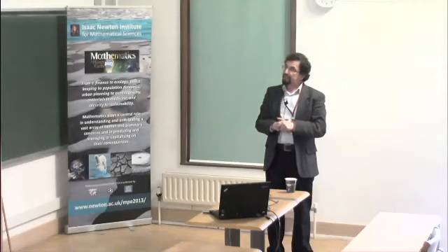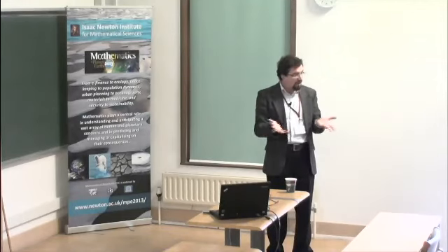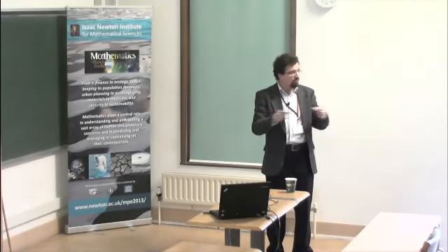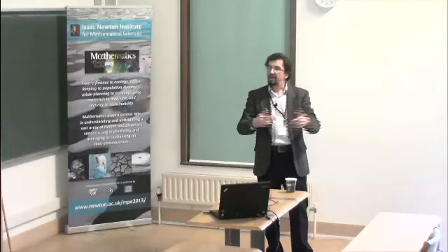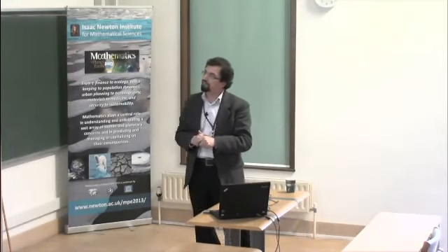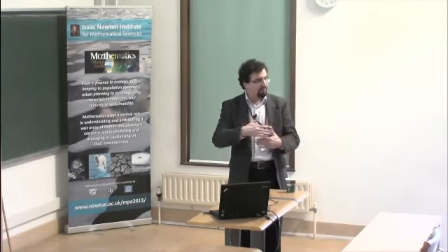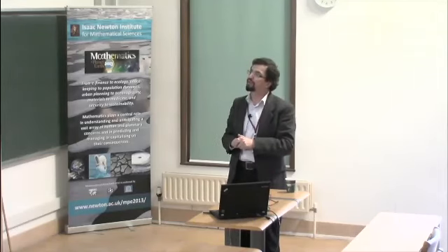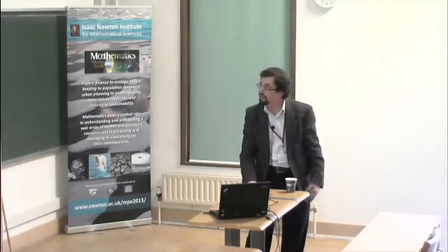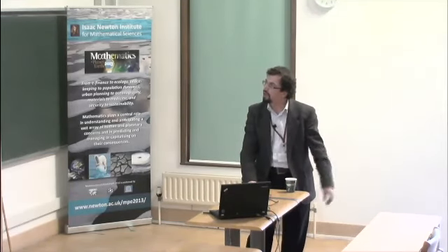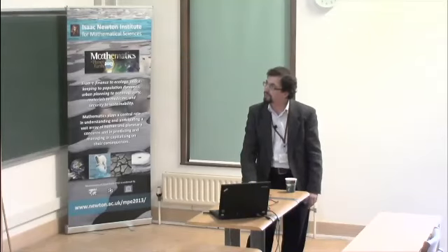But what is interesting is that X-ray shows no traces of molecular smecticity or molecular periodicity. And it's a peculiar case of a nematic phase that has some elements that are periodic, but this periodicity is apparently not at the molecular scale. So I don't know whether there is a clear understanding of this phase.